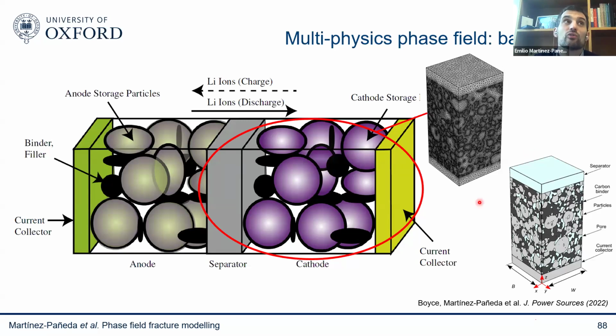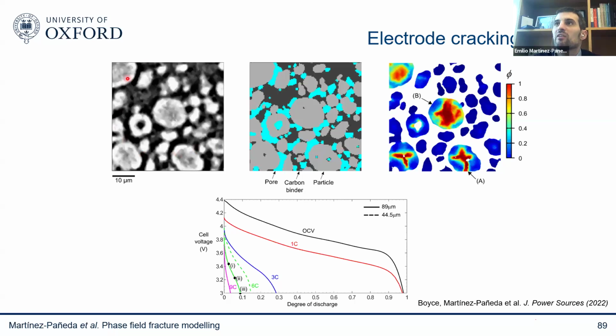We can go from the XCT scan to a finite element model. We can segment that XCT scan into the finite elements. So we can not only model those particles, but we can see how particles interact with each other and what is the role of other phases that come here, like carbon binders, pores, and other secondary phases. You see an example here. This is what you get from the XCT image. This is what you put in your finite element model. And finally, you run your simulations.